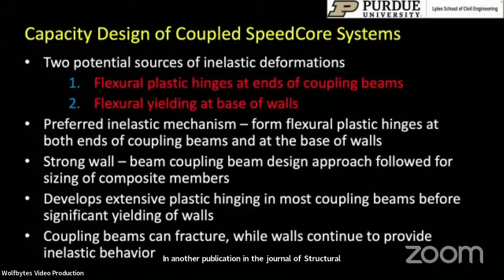We identified two sources of inelastic deformations. You can form flexural plastic hinges at the ends of coupling beams, and you can also form flexural yielding at the base of the walls. Our preferred inelastic mechanism was to form flexural plastic hinges at the ends of both coupling beams and at the base of the walls. But we decided to implement a strong wall, weak coupling beam design approach in order to size the composite members. What this means is that you develop extensive plastic hinging in most of the coupling beams along the height of the structure before you get significant yielding and fracture at the base of the walls. The coupling beams can even fracture while the walls continue to provide inelastic behavior.